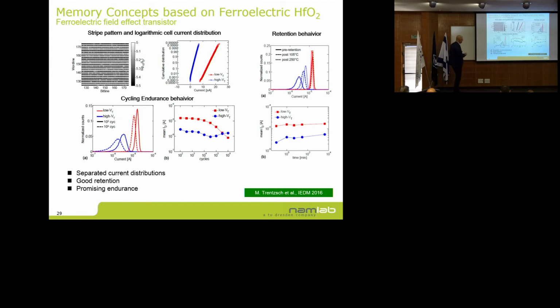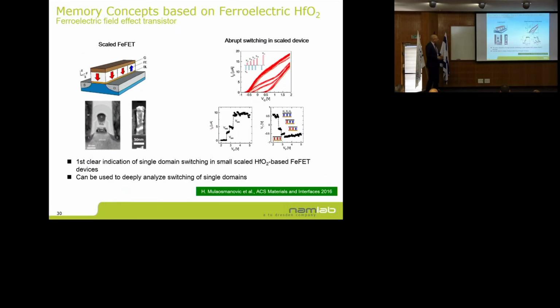And also the FEFET works quite well for a first approach. So you can write something into the memory. You get some window between all the cells. It's still quite narrow, but it's there. And it behaves quite well after retention and also after cycling. So it's demonstrated that the material is not just in theory, but also practical, very easy to integrate in a modern CMOS process. When we did that, we found a very interesting side result.